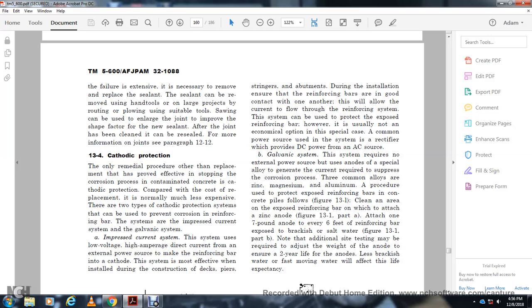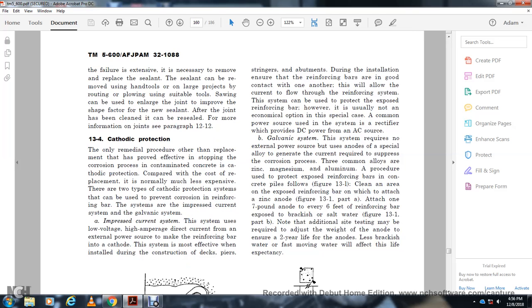The common alloys are zinc, magnesium, and aluminum. The procedure to protect the exposed reinforcement bar in a concrete pile is shown in figure 13.1. Clean the area of the exposed reinforcing bar on which the zinc anode is to be attached. Figure 13.1 part A: attach a 7-pound anode to every 6 feet of reinforcement bar exposed to brackish and salt water. Figure 13.1 part B. Note that additional site testing is required to adjust the weight of the anode and ensure a 2-year life of the anodes. For brackish water, fast-moving water will affect the life expectancy.